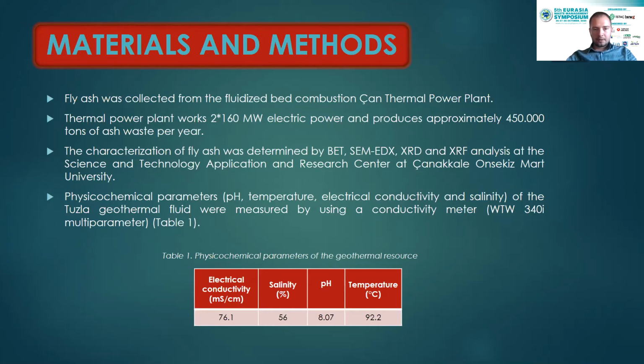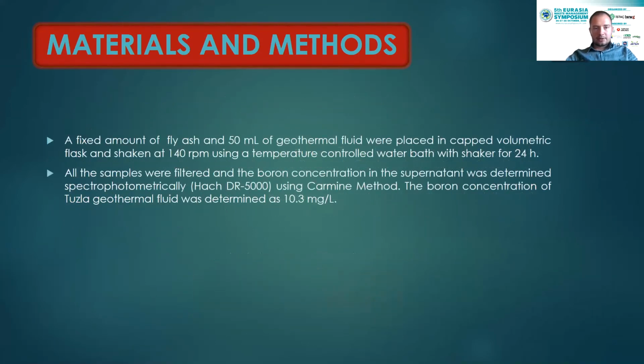Physicochemical parameters of the Tuzla geothermal fluid were measured by using a conductivity meter. In Table 1, physicochemical parameters of the geothermal resource. A fixed amount of fly ash and 50 ml of geothermal fluid were placed in capped volumetric flasks and shaken at 140 RPM using a temperature-controlled water bath with shaker for 24 hours. All the samples were filtered and the boron concentration in the supernatant was determined spectrophotometrically using the Carmine method. The boron concentration of Tuzla geothermal fluid was determined as 10.3 milligram per liter.